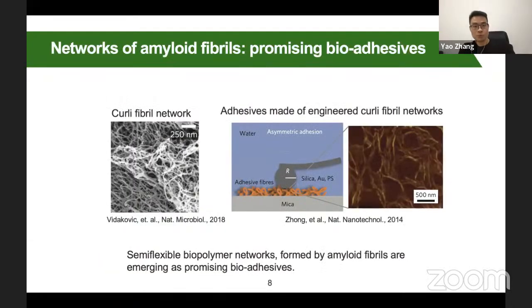So if we use this curli fibril as a material, it has excellent adhesion property. Actually, researchers already use this bacteria to fabricate this kind of network, only formed by this curli fibril. So you can see, this microstructure just has the curli fibril. And if you test its adhesive ability using AFM, it shows very good adhesive ability. So this kind of material is a promising bioadhesive.